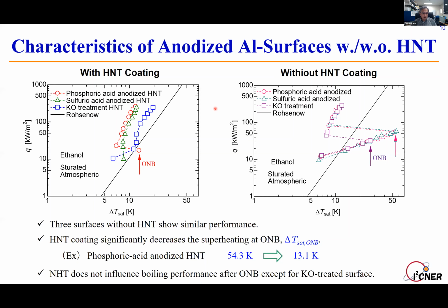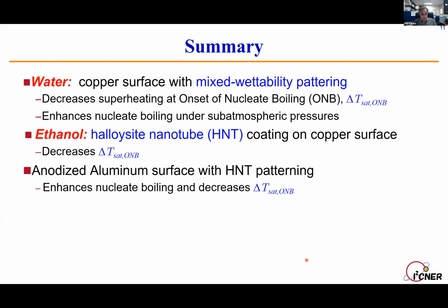In both cases, when boiling occurs, the boiling characteristic on both anodized surfaces has almost the same nature, but the different thing is the onset of nucleate boiling. So by HNT coating, we can decrease the onset of nucleate boiling surface superheating from 54.3 Kelvin to 13.1 Kelvin. It's a significant improvement. Okay, so this is the last slide of my talk.